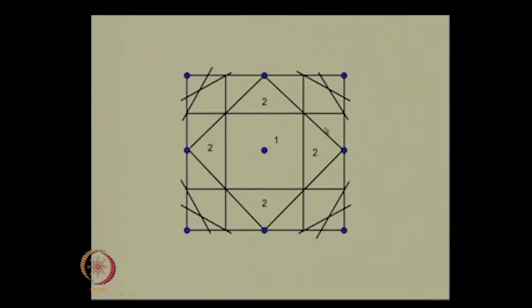Similarly, you cross one more Bragg plane, that means you have now crossed 2 Bragg planes, and you do not cross a third Bragg plane, that would put you in this region, that would then be the third Brillouin zone, and there are several such locations where you would effectively be accessing the third Brillouin zone. So, these are all the third Brillouin zone. If we continue the exercise further in exactly the same manner, we can identify the fourth Brillouin zone as those 4 locations, or at least those locations that you see there, and then you continue this process, at least within the context of the figure we have drawn, this is then the 5th Brillouin zone, and this is finally the 6th Brillouin zone. Okay.